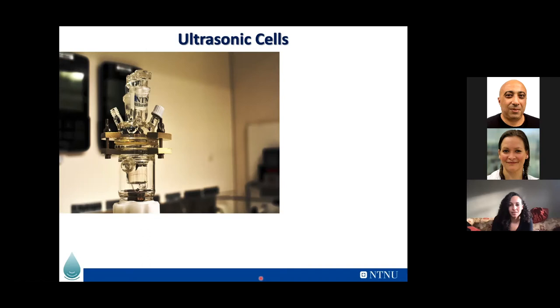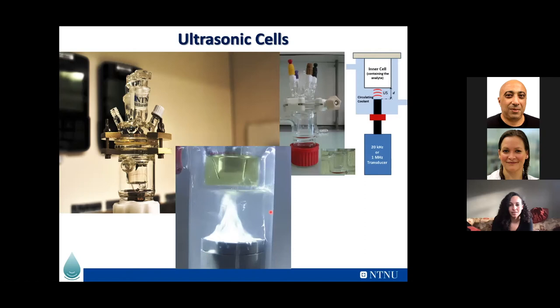Okay, so another image here. You could look at different cooling fluids, because obviously when you use ultrasound, you have an increase of temperature, and this temperature may also affect your electrochemistry or your chemistry. So you need to use some kind of coolant. This coolant was a silicone oil. We used it under pressure, and we also wanted to have all cavitation events happening in the inner liquid here, which is basically a platinum solution, rather than in the silicone oil.